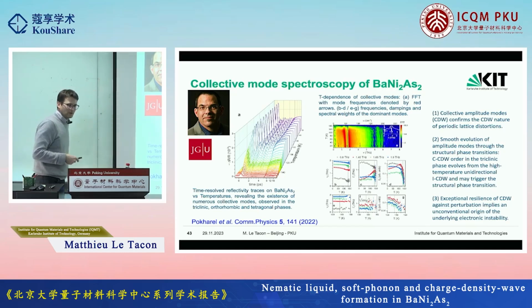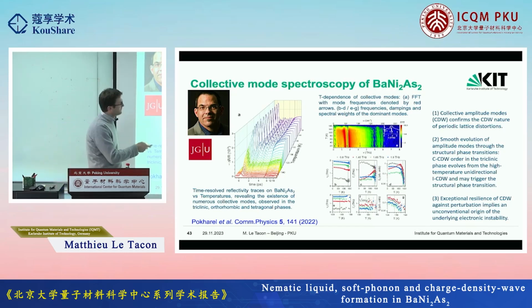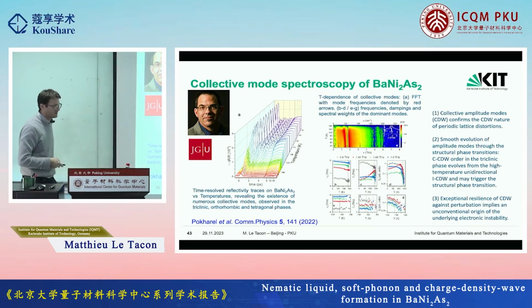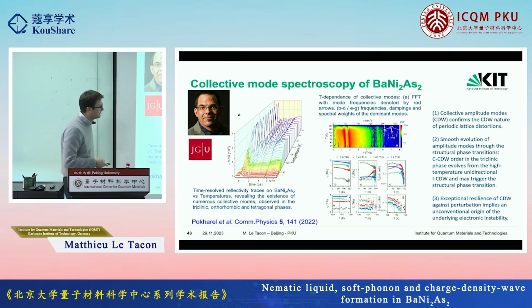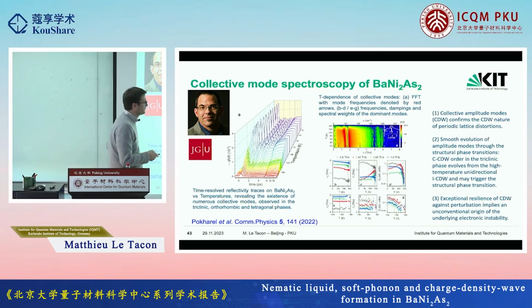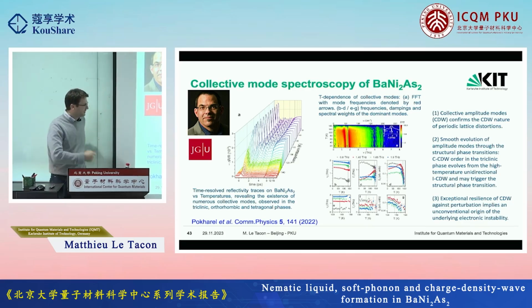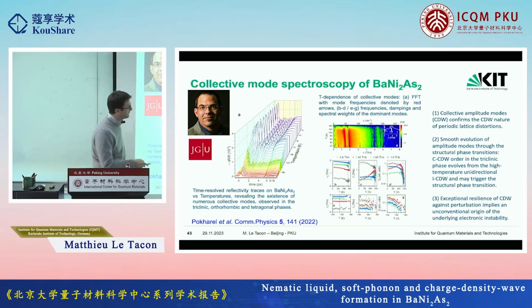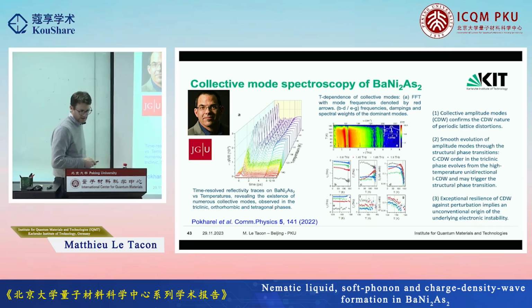In echo maybe to what we discussed on Monday, where we had also done some collective mode spectroscopy together with Jure Demsar in Mainz. And what he found, also a somewhat surprising result, is that those charge-density wave excitations are very strongly resilient. You can use a very large fluence and very strong laser intensity, and you basically hardly kill them. So they survive, they're very, very robust.